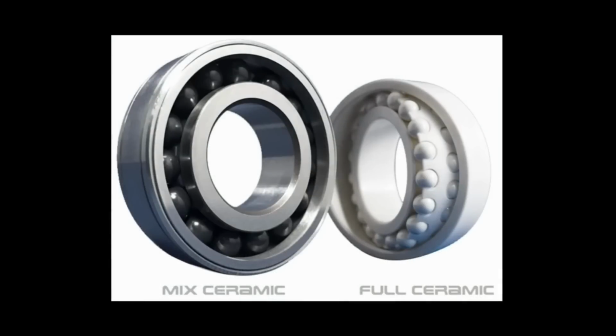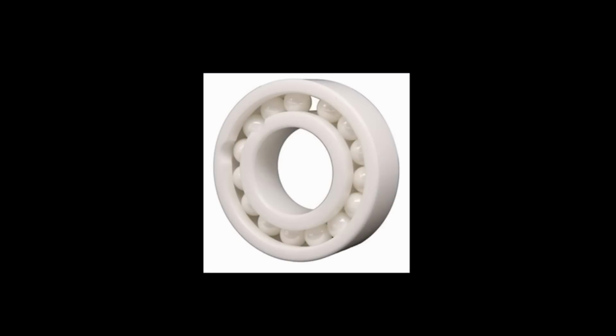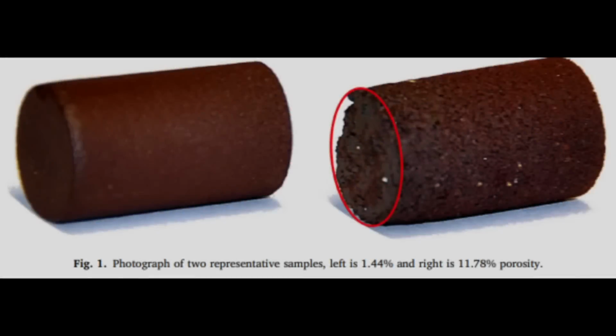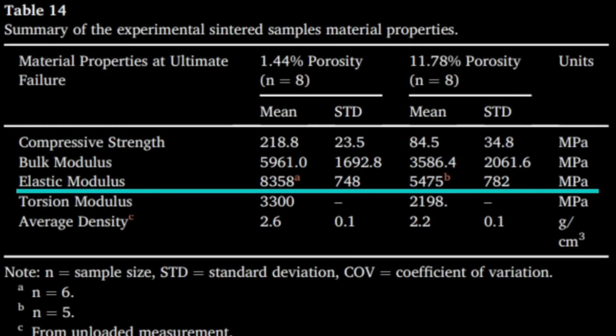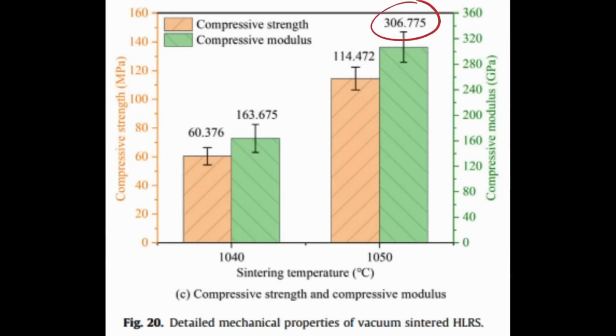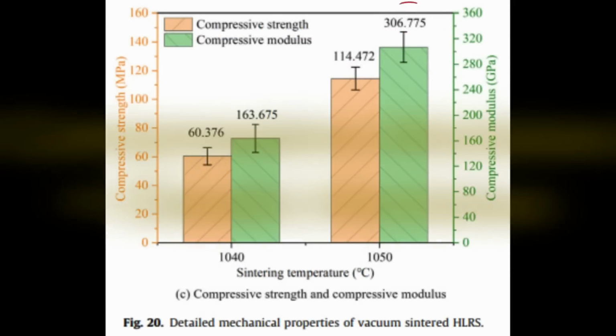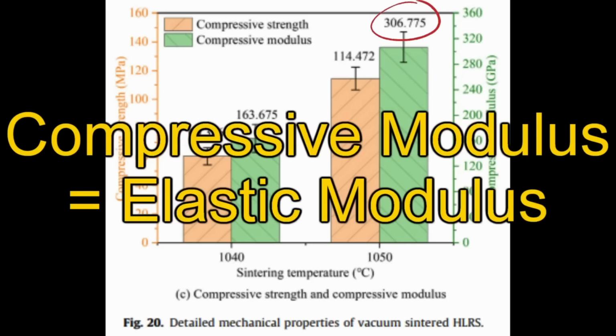Also, it's worth noting that we do actually make ceramic bearings and wheels here on Earth today because of their superior rolling resistance. So this is not completely without precedent. The real issue is, and the reason this hasn't really been discussed before, is that sintered regolith has generally always been much more of a porous type ceramic, with high porosity leading to brittleness and a much lower elastic modulus, orders of magnitude less, like around 8 gigapascals versus the 306 gigapascal sintered regolith created by the authors of this recent paper, published in June of 2024.